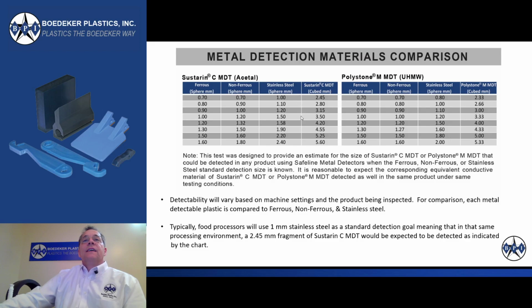Plastic, on the other hand, was not as detectable, as we already mentioned. Actually, we saw the metal detectable acetal vary from 2.45 millimeter cubes all the way up to about 5.6 millimeter cubed. And the same held true when we looked at the data on the right-hand side, which is the same sets of data, but in comparison, we compared them to a metal detectable ultra-high molecular weight polyethylene, the Polystone material. And in that case, we saw plastic that varied from 2.33 millimeter cubed on down to 5.33 millimeter cubed.